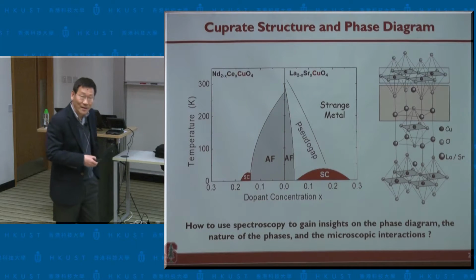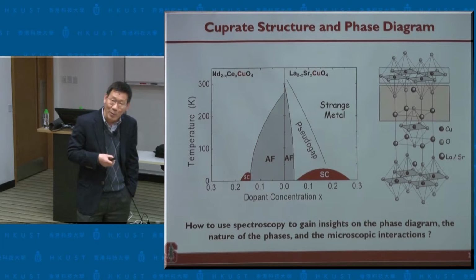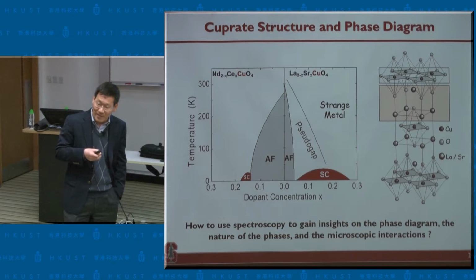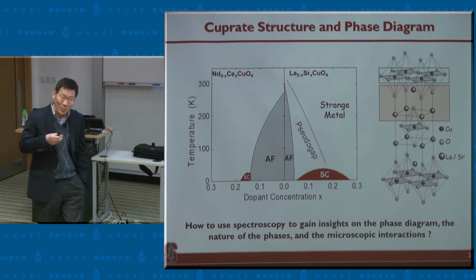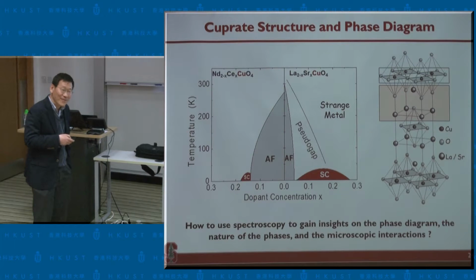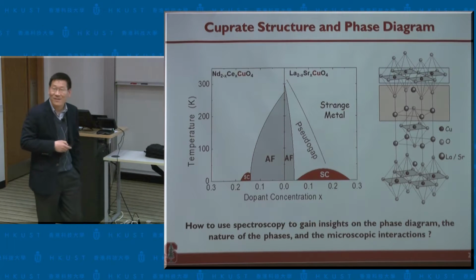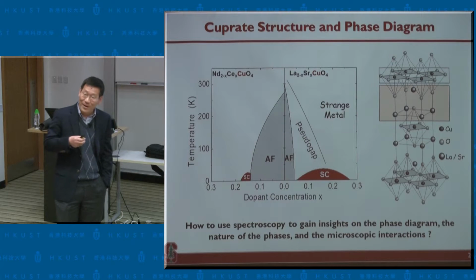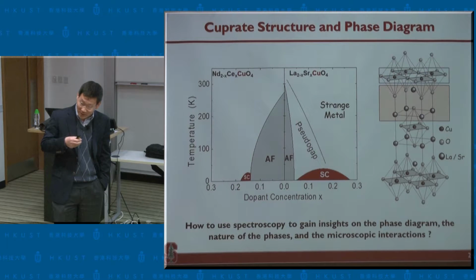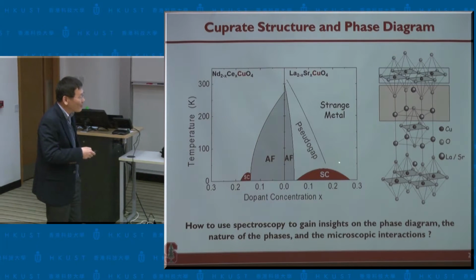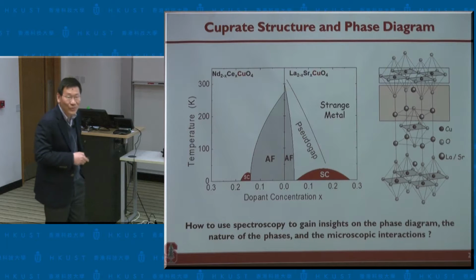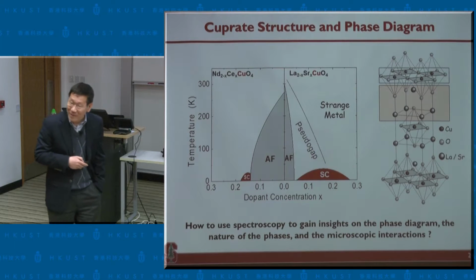The conventional way to understand superconductivity, we have very good handling, thanks to Lev Landau, that the Fermi liquid state of the normal state, and that instability and gauge symmetry breaking of that led to superconductivity. Now we have a situation where we actually know the superconducting state, they're quasi-particles. It's a D-wave superconductor. But what we don't know is the state whose instability leads to the superconducting state. That's one of the challenges.